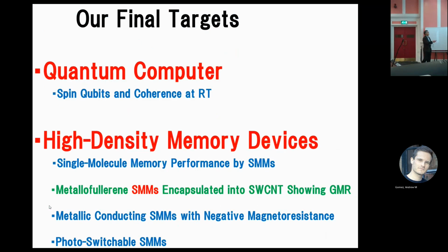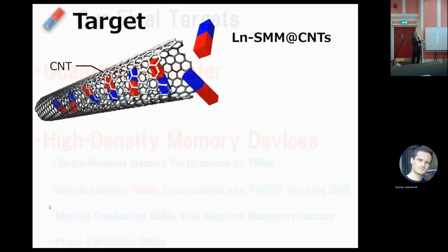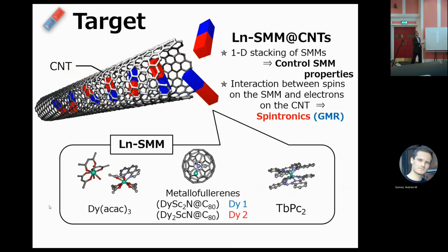So let's move to the metallofullerene single-molecule magnet encapsulated in a single carbon nanotube showing giant magnetoresistance. Every time I use a single-molecule magnet instead of a classical magnet to overcome Moore's limitation. Single-walled carbon nanotubes are 70% semiconducting, 30% metallic. We inserted in the single-molecule magnet; conduction electrons and the local single-molecule magnet interact to show negative magnetoresistance. For this purpose, we usually use a deposition of one metallofullerene single-molecule magnet and also double-decker phthalocyanine.